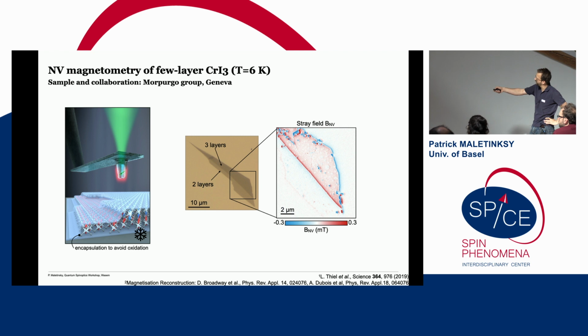And lo and behold, we saw stray fields emerging from these flakes. You see here that the bilayer shows almost no stray field. That's because adjacent layers show antiferromagnetic ordering. The trilayer, however, does show a stray field, and you see immediately that the stray field only comes out at the edge. That is exactly what you expect for a fully polarized two-dimensional magnet, which in this case, for an out-of-plane magnetization, you can just represent by an edge current going around the flake, and that generates this field.